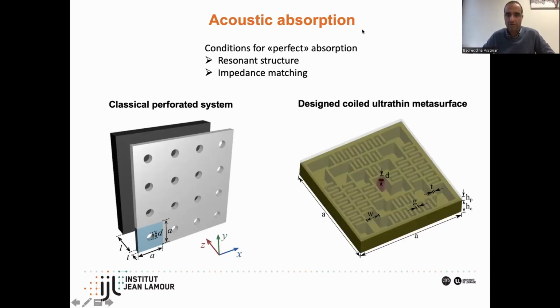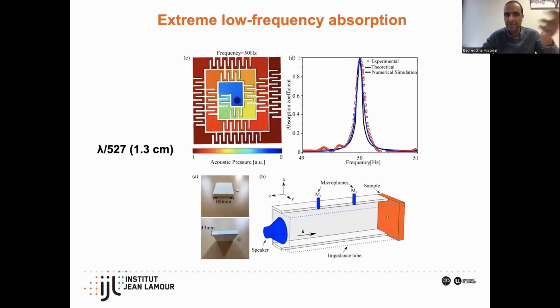This kind of system is interesting because in general, if you would like to enhance absorption, or get a perfect absorption, you must simultaneously realize 2 conditions. The first one is you need a resonance structure. And the second one, you need a perfect impedance matching between your system, your metasurface, and the surrounding air, which is extremely difficult to realize based on the design. So those are the 2 conditions that must be realized simultaneously in order to get a perfect absorption. That's what we did for different structures. Here, for example, we developed that in 2019, 2020 about these labyrinthine systems, theoretically, experimentally, and numerically.